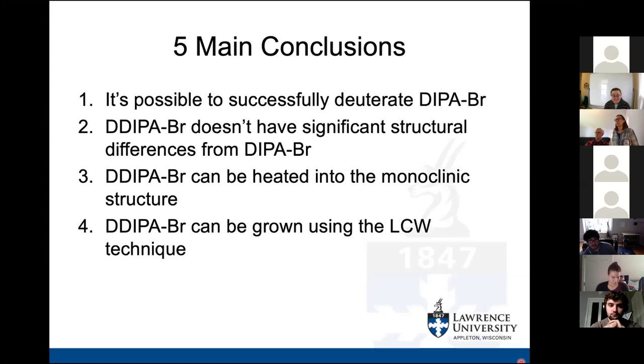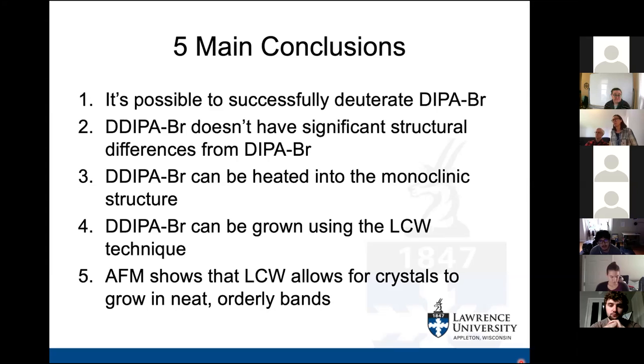4, deuterated Diisopropylammonium can be grown using the LCW technique, and this growth is optimized, as visuals from the scanning laser microscope told us. The 5th and final conclusion is that atomic force microscopy proves that the LCW technique creates good crystal growth that happens in neat, orderly bands. This is important because if the deuterated Diisopropylammonium crystals are on the substrate, they need to be in neat, orderly rows in order for the current to pass through the crystals. From this research, it seems that deuterated Diisopropylammonium is structurally the same as its non-deuterated counterpart, and that information from the deuteration studies can be applicable to studies on the non-deuterated counterpart.